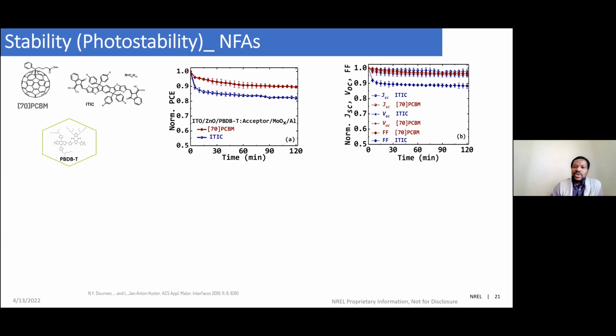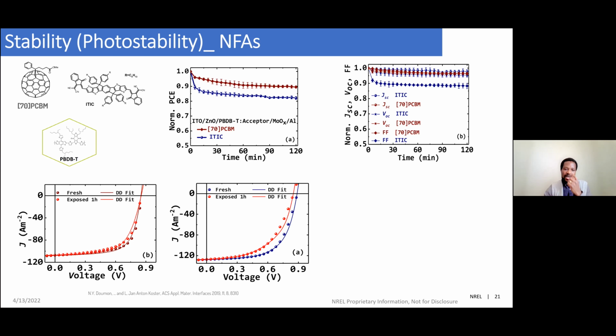And what we realize is that it loses a lot in terms of the fill factor. What would be the reason? Why would this be more advantageous in efficiency, but in terms of stability, photostability, that's not working? So we try to look at this from drift diffusion simulation done by Vincent in the audience today, which shows that